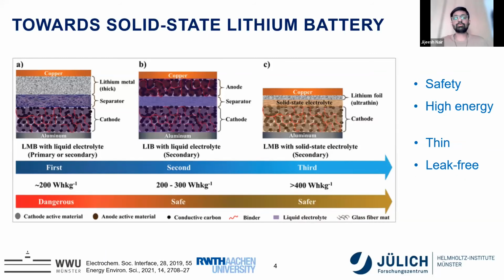But now the third revolution could be the lithium metal battery, in which we can use a very small amount of lithium foil, or even, as we mentioned, anode-free or lithium-metal-free batteries. So when we use lithium-metal-free or lithium metal based batteries, we have to resist dendrite formation. And one of the best ways is moving towards solid state electrolyte. This will surely increase the safety. It can reduce the size of the battery, so energy density can be improved. We can produce thinner batteries, and as no liquid is there, it is completely free from leakage of the electrolyte.